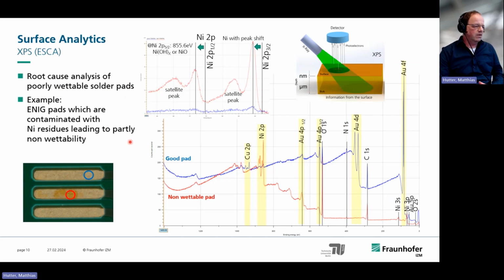What is really important, not only for soldering, this is an example for a solder pad, but also for sintering, is that the surfaces are clean. We would like to really be sure that our surfaces are clean. For this purpose, we use the XPS analysis method. So we have an X-ray which bombards the surface, and the photoelectrons which are ejected are then detected. And then you can really see whether your surface, like in this case, is contaminated with nickel. It should be pure gold and not nickel on the surface.